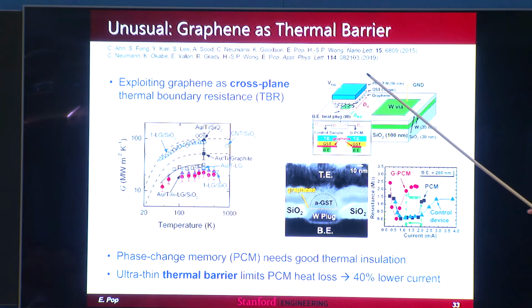More recently, this paper actually just came out in APL. So I made sure to update the slide last night. We've been able to do this with MoS2 as a heat blocking layer, just MoS2 by itself. And it's another 20% or so reduction of programming current compared to graphene. So it turns out these things are pretty good as thermal insulators, deliberate thermal insulators in a certain way.